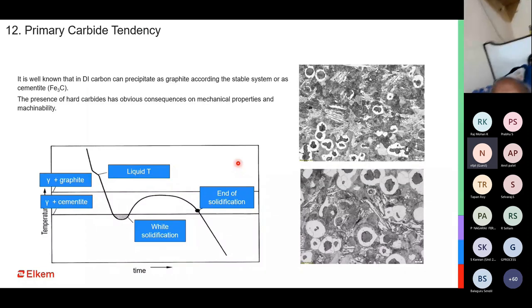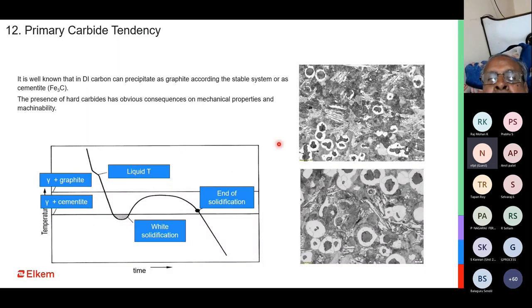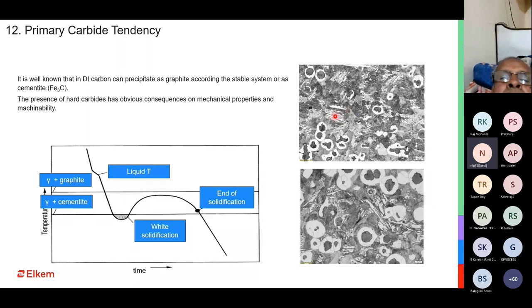So what we are trying to say here is that we have to make sure that our carbon comes out as graphite and does not go back and combine with iron to form Fe3C, which is cementite or iron carbide. The presence of these carbides, which are very hard phases, has an obvious consequence on the mechanical properties as well as the machinability of the casting.